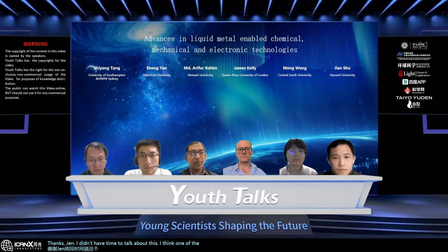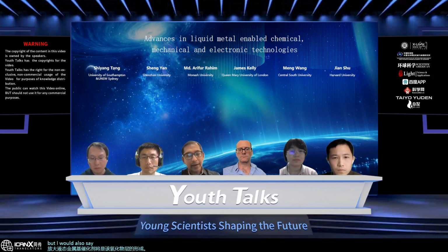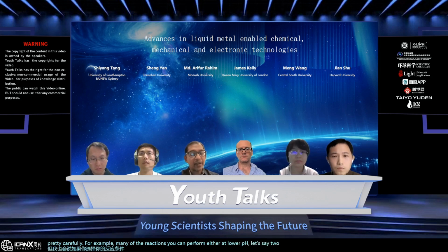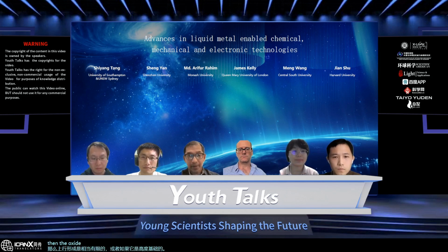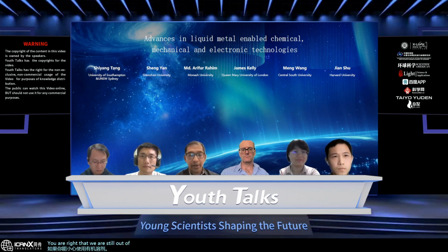I think one of the most problematic aspects of scaling up liquid metal based catalysts would be this oxide layer formation. But I would also say that if you choose your reaction conditions carefully, for example, many of the reactions you can perform at lower pH, let's say 2 to 3 or even less, then the oxide formation is pretty limited. Or if it is highly basic, then the oxide formation is also limited. And also, if you can carefully use organic solvent. So you are right that we are still kind of out of the biological realm, just because of the oxide formation.